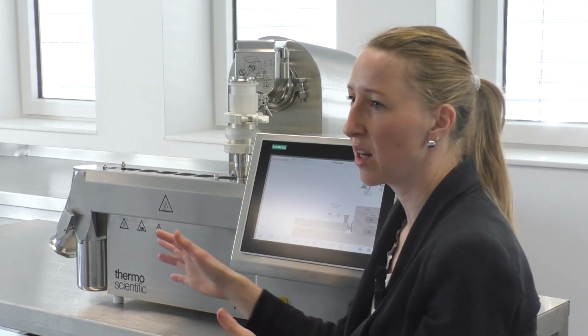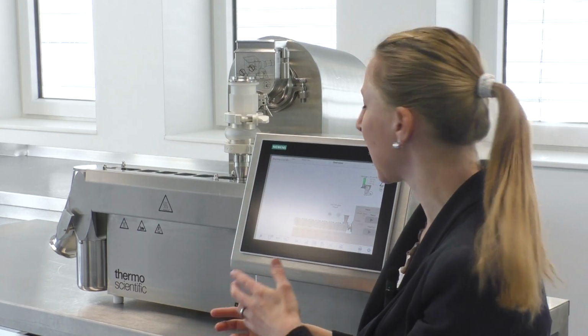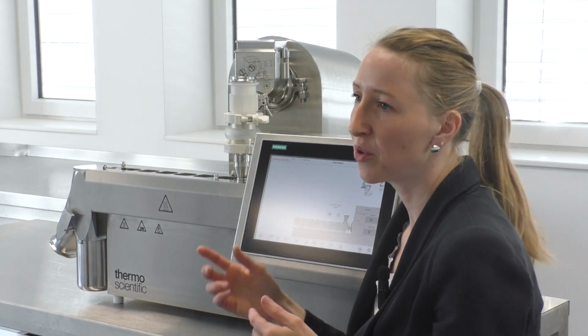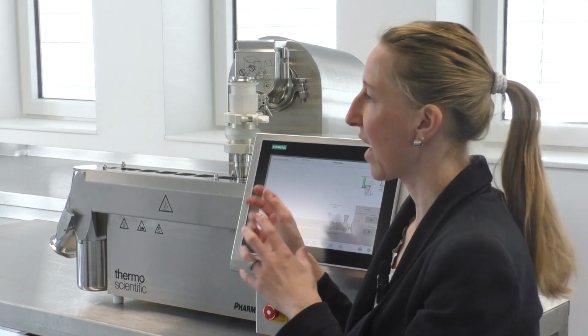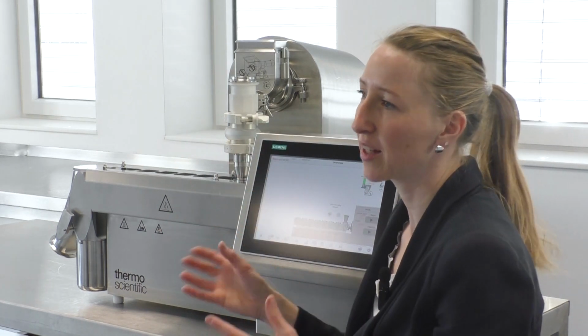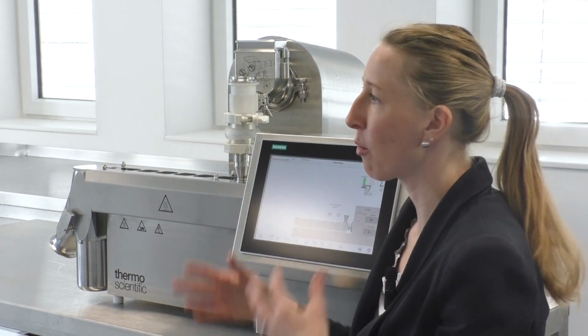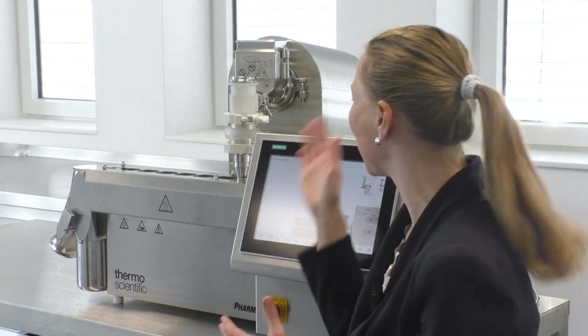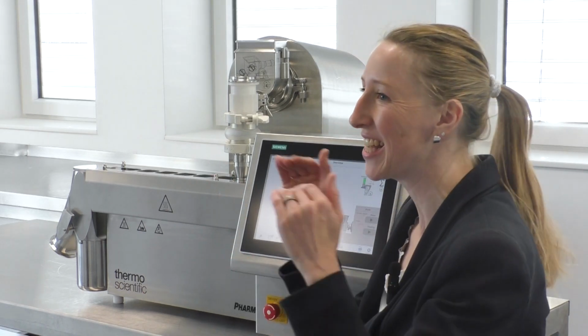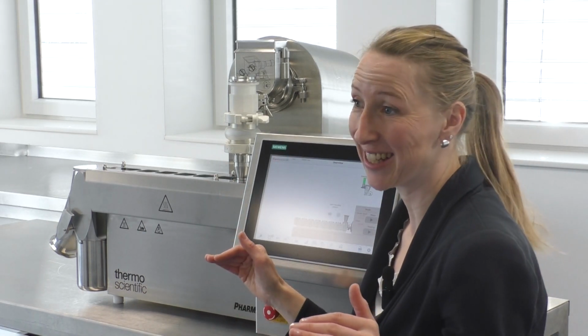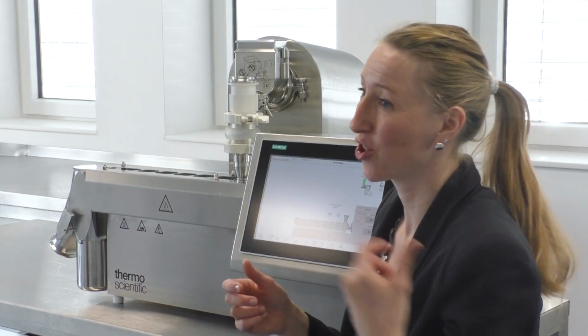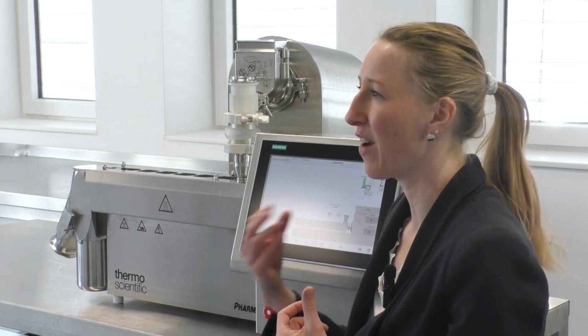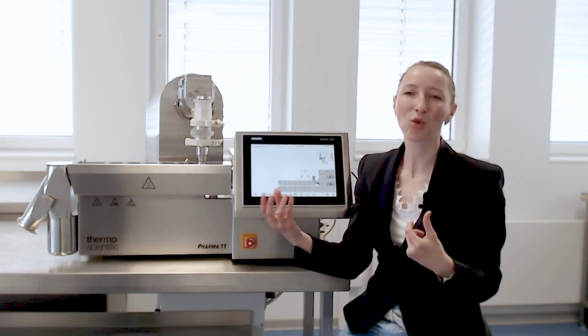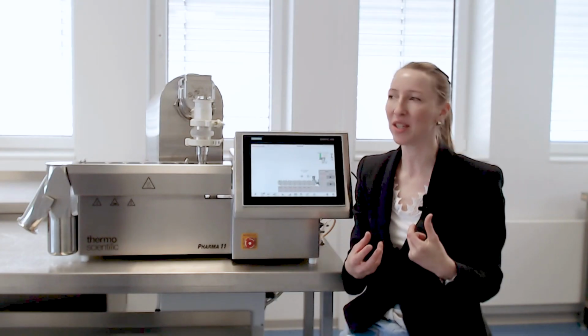So the setup was done. I chose one screw configuration, and then I could add more material, reduce the screw speed, and for each setting, collect material. I didn't have to make a new batch, but just produce continuously, change the setting, wait for steady state, and once I had it, collect the material. So it was a very quick screening of process settings that I could do here.